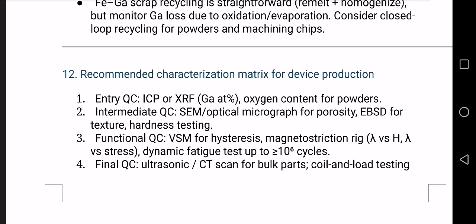Finally, let us talk about quality control, because no device survives without QC. This is not just testing, this is risk management. Entry quality control: incoming materials, chemical composition verification. At the start, ICP, OES or XRF confirm Ga atomic percent tolerance, very tight, typically 0.2 at percent.